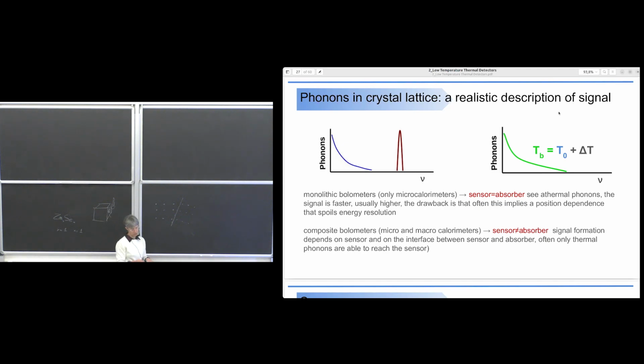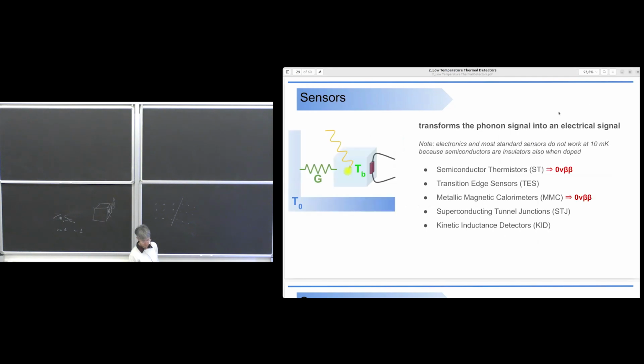In other cases, the sensors are films deposited on the crystals. And in that case, you have a less important interface, and it is possible that you are transmitting athermal phonons. But still, a lot of groups have experienced the problem of a poor energy resolution when we transmit athermal phonons. And therefore, often the choice is to have an interface that is maybe not perfectly thermal, but in between the phonons that are produced immediately after the excitation and recombination of ions and electrons, and the full thermalization.